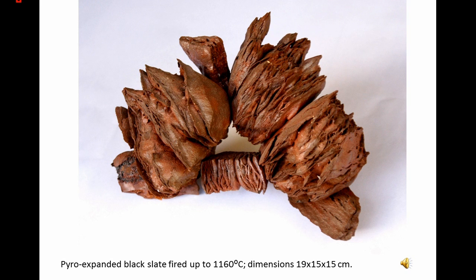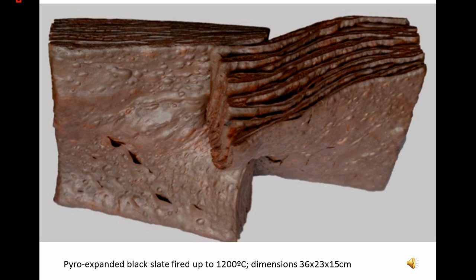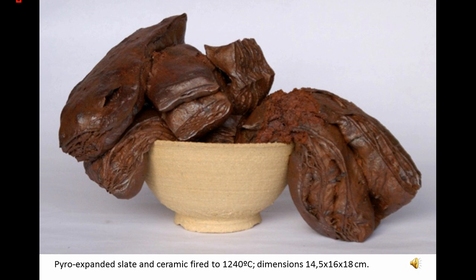The mortises of a slate piece in another one are carried out by cutting an entrance in one of the pieces, or in both. The width of the cut must be related to the thickness of the piece to be encased. In the adjacent area to the mortises, the expansion is mutually constrained, resulting in rich expressiveness. Interactions between slate elements and ceramic elements were explored, and one example is presented.